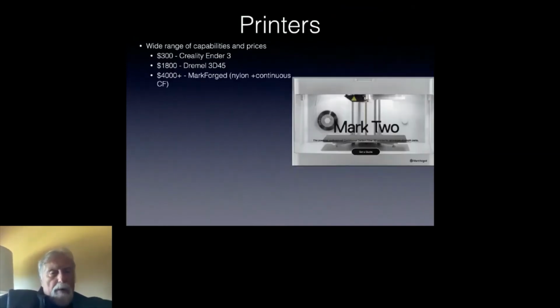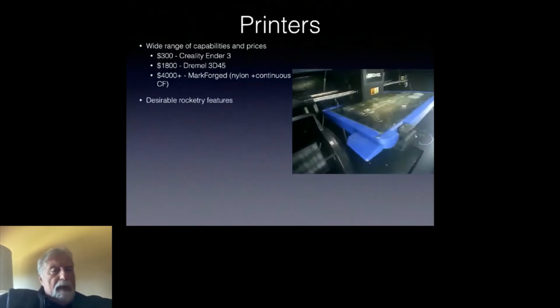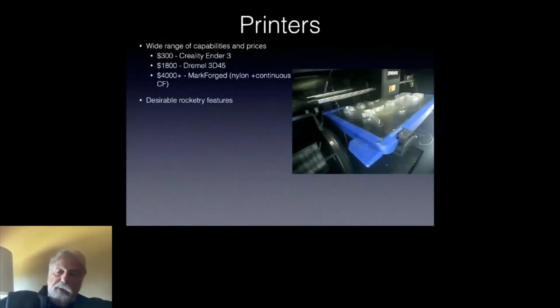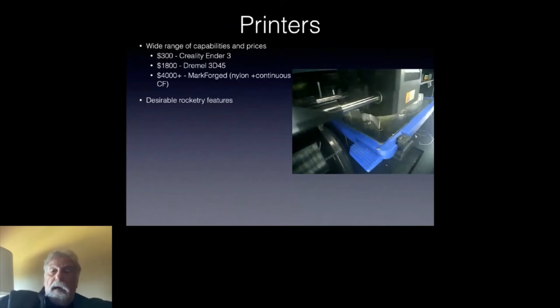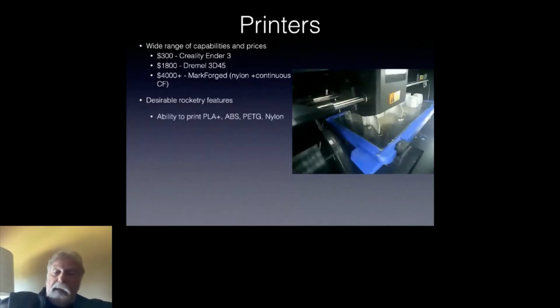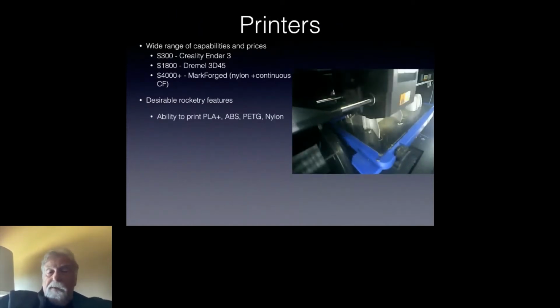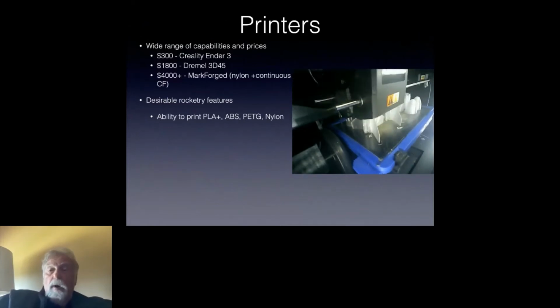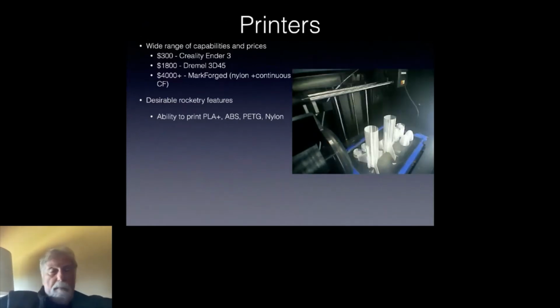And then with my partner, John Coker, we're now using MarkForged, which begins at about $4,000 and goes up to about $10,000. We're looking at nylon and continuous carbon fiber and a strength profile that begins to look a lot more like aluminum, so some desirable rocketry features. So you see the printer here printing those same little rockets. The ability to print PLA Plus, ABS, PETG and nylon is really important, and I would use any of these materials in different places.